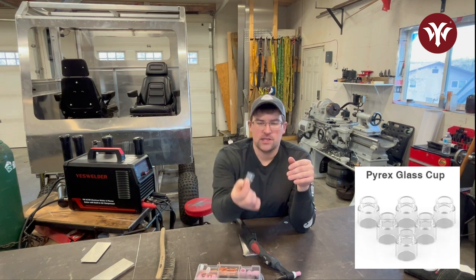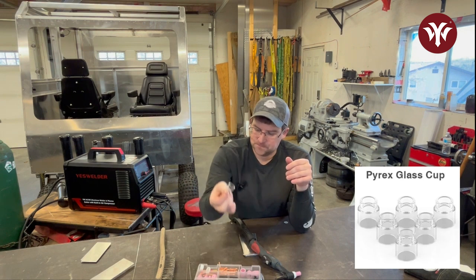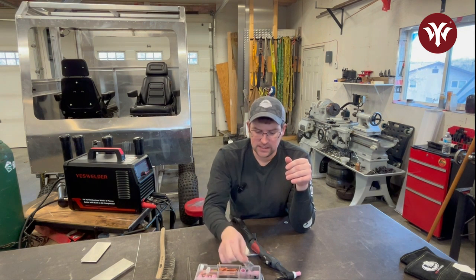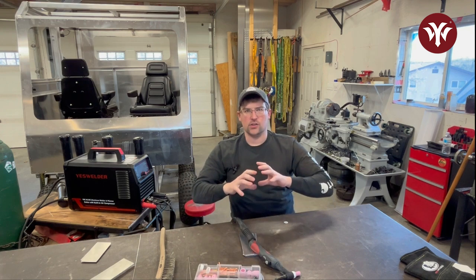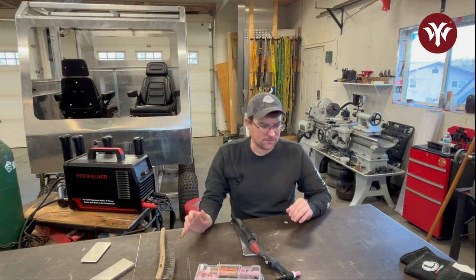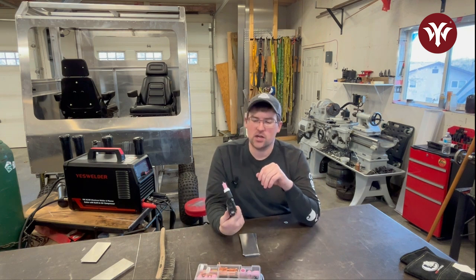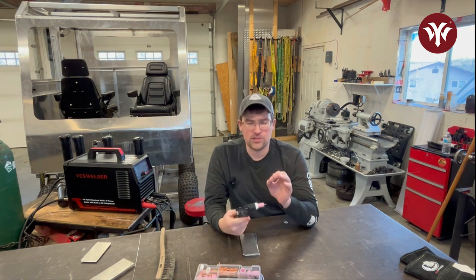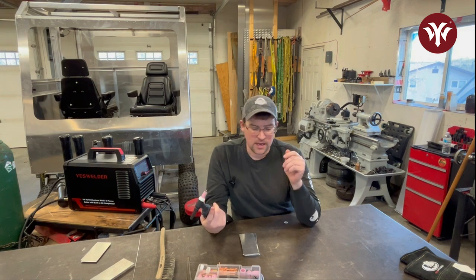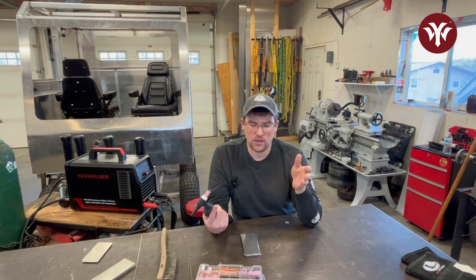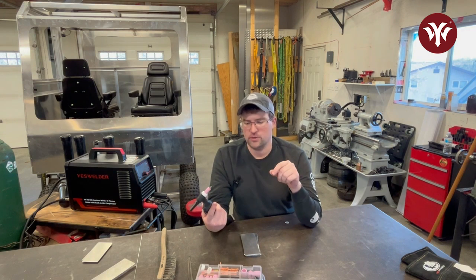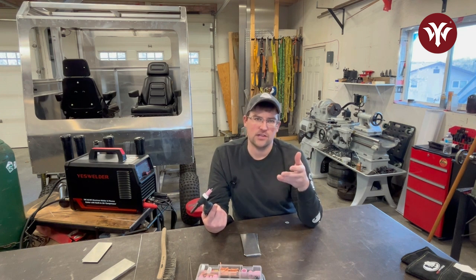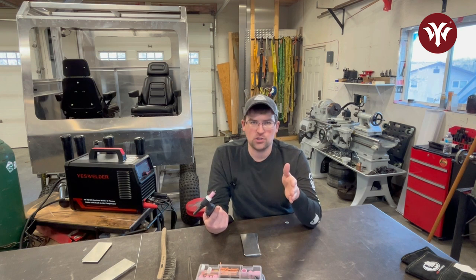The one thing you won't be using is these Pyrex nozzles you typically see with welding stainless, because when you're doing stainless, you want a very wide gas coverage. You're DC TIG welding, it's a whole other ball game. So again, if you're just getting started, don't think too hard about it. If you're using 3/32, go with a number 6. If you're using 1/16 of an inch, you can probably get away with a number 5, maybe even a number 4. That's getting pretty small, and vice versa. If you go to 1/8, you can go up to a number 7 or a number 8 nozzle size. It's really up to you.